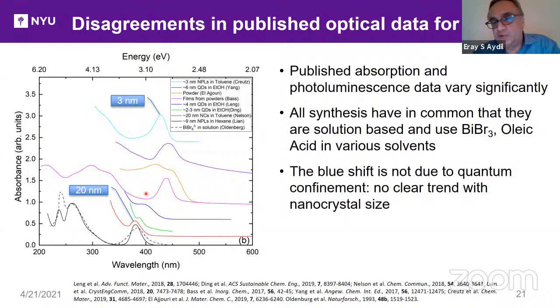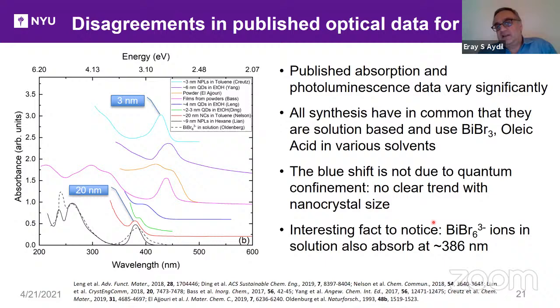And there are others that don't follow the trend. You notice sort of a lumping around 380, 390 nanometers and a lumping around 430 nanometers. There's one interesting fact that I would like to point out. If you make a liquid solution of bismuth bromide, BiBr6 3- ions, they also absorb at 386 nanometers. There are no nanocrystals or solids here, it's just an ionic solution. That absorption is this dashed line here that was collected back in 1993 by Oldenburg. Note that it is almost identical to some of these absorption spectra that are presumably Cs3Bi2Br9 colloids.